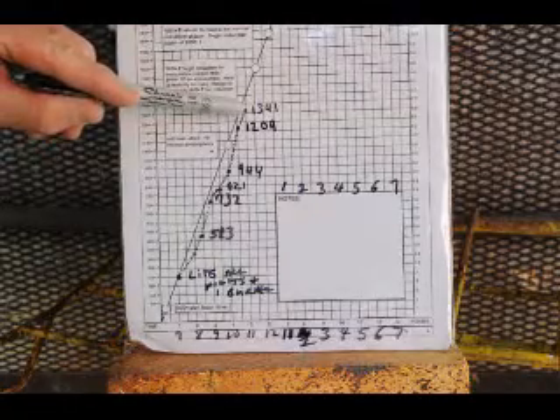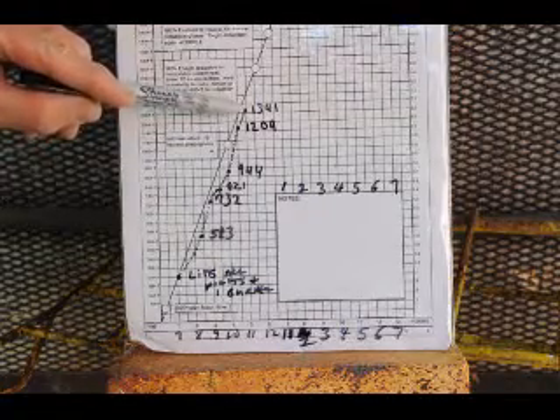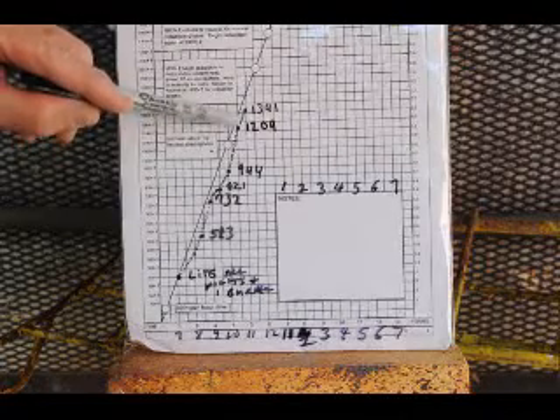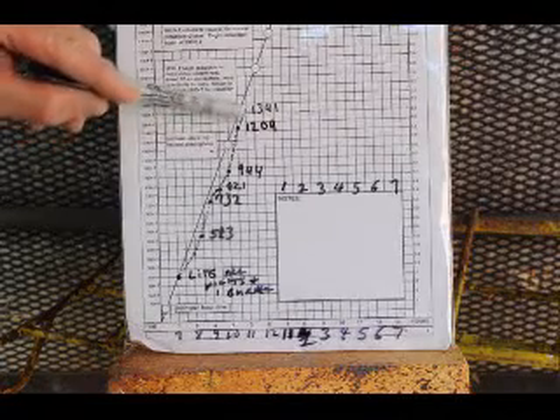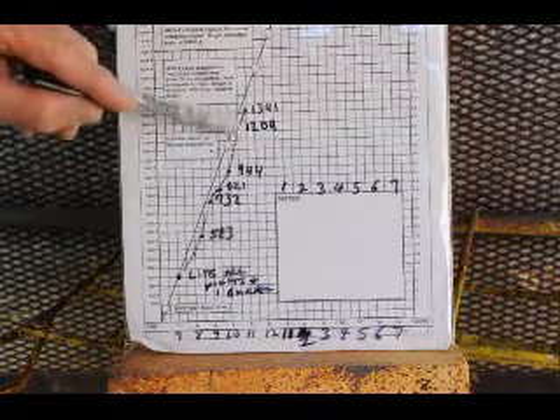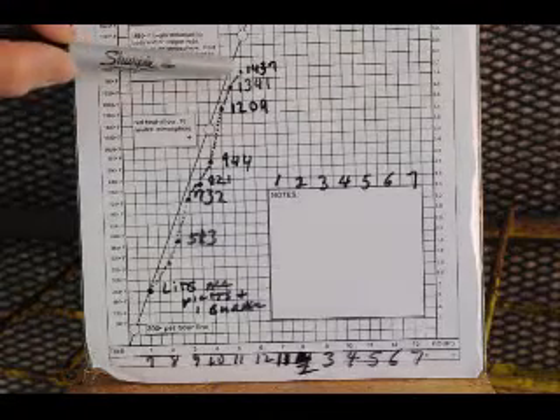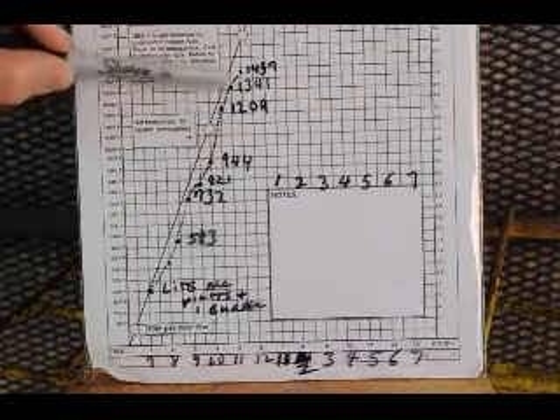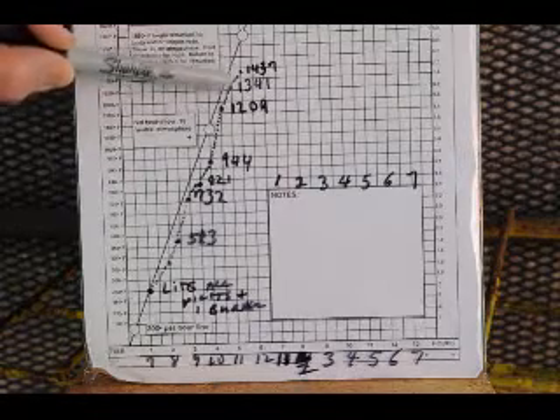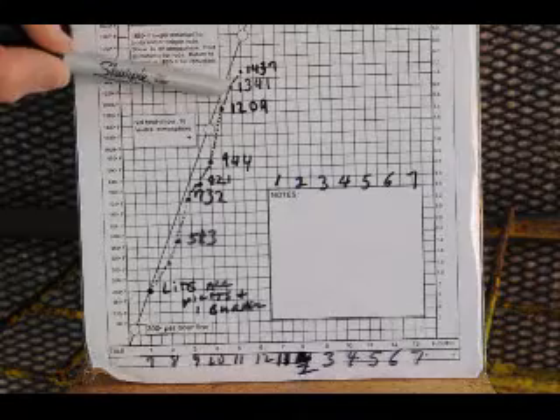It's now 11 o'clock. Temperature is 1341. Gas flow is on 2 units, and we're still rising at 300 degrees an hour, so there's no need to increase the gas at this point. We'll wait another 30 minutes. 11:30. Temperature is 1437, and the rate of climb has tapered off, so I'm going to increase the gas flow to 3 units of flow for each of the 6 burners.